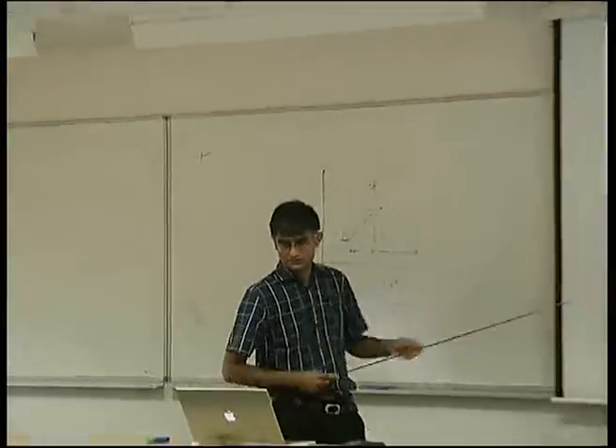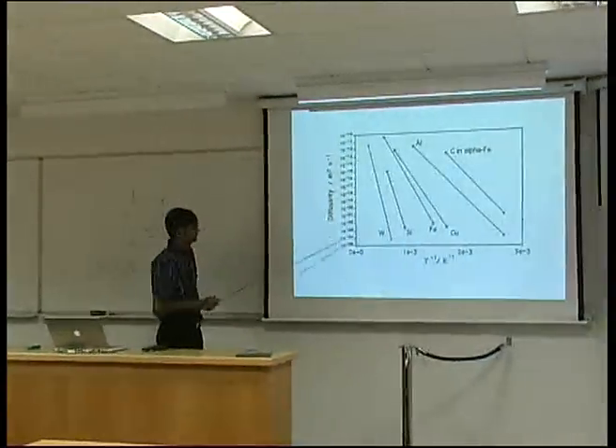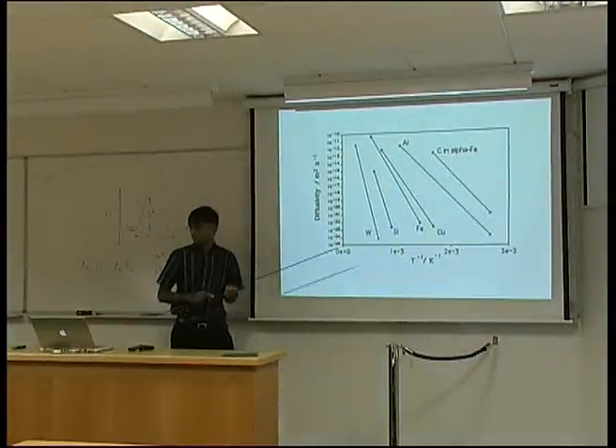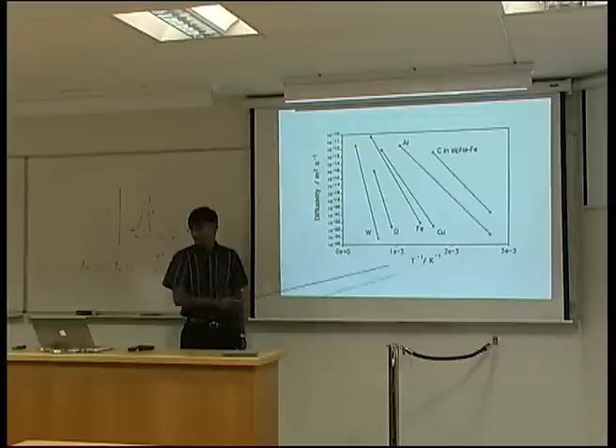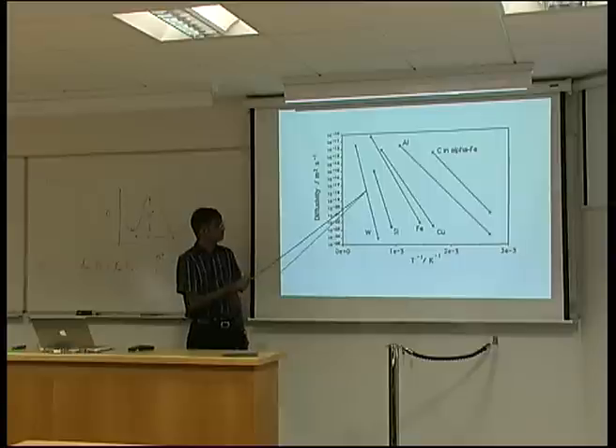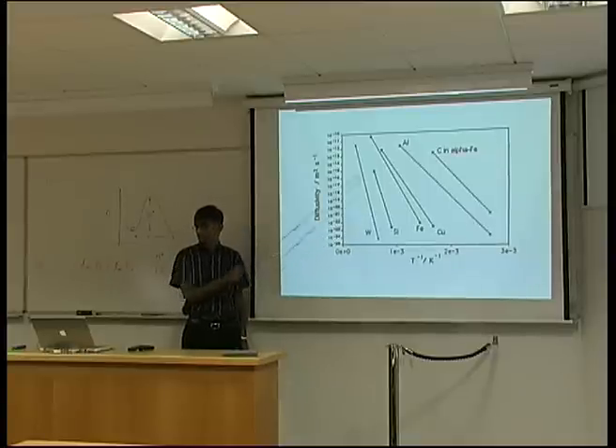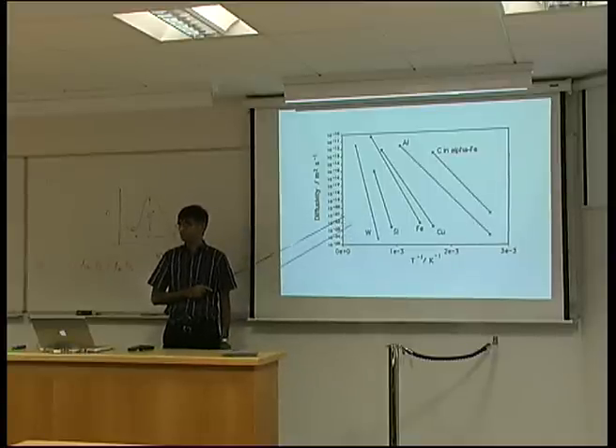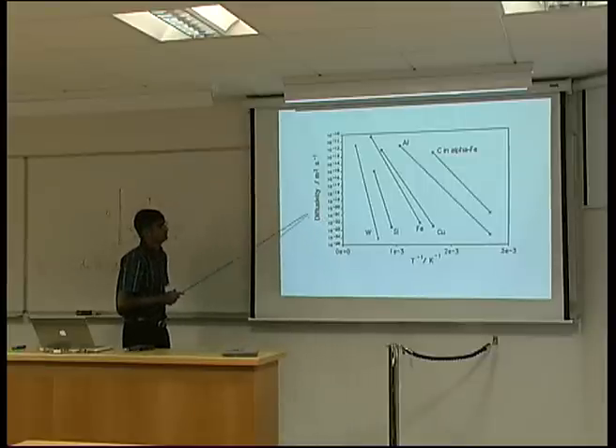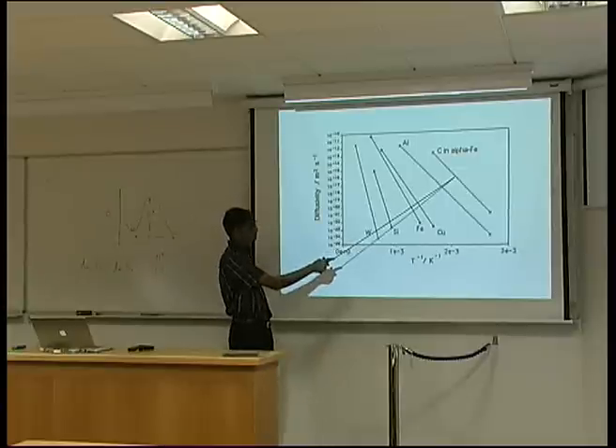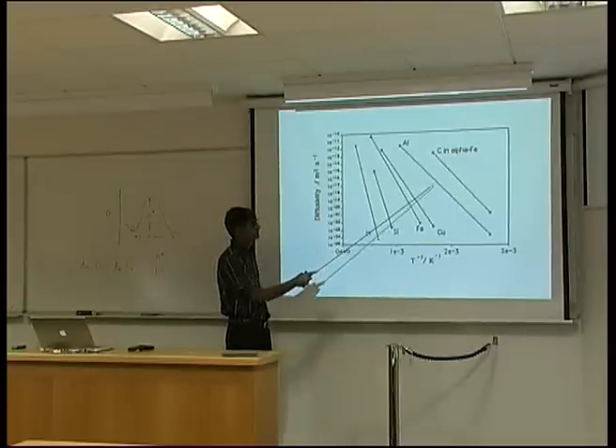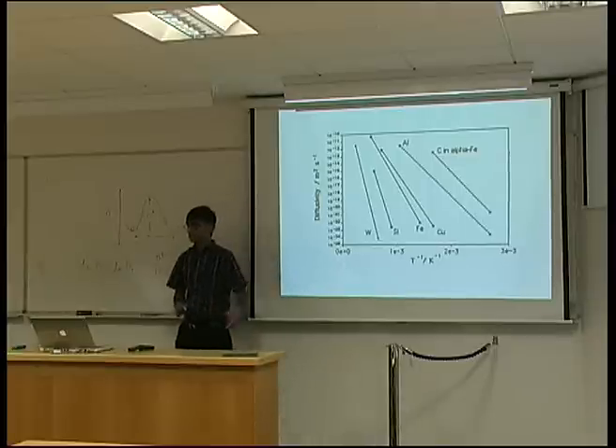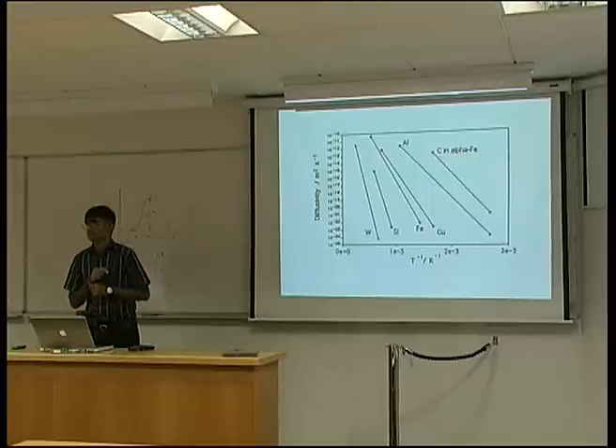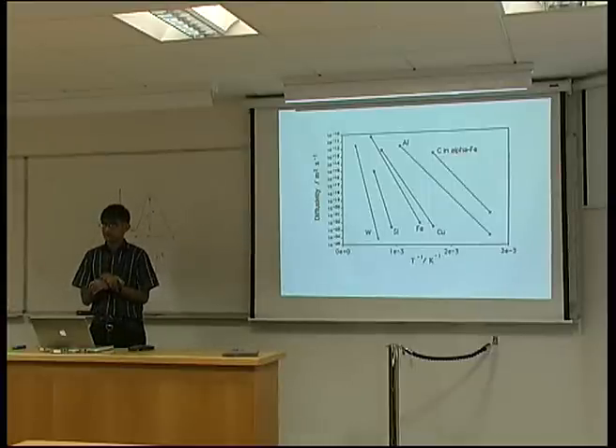So here are some typical graphs where we are plotting the logarithm of diffusion coefficient versus the reciprocal of temperature. And you can see that they are straight lines. I mean, this is just my drawing, that there are points at each end, because I didn't want to plot several points. Okay, that's laziness. But obviously you have to have more than 2 points to know that it's a straight line. Okay. What I'd like you to comment on is, why is the diffusion coefficient of carbon so much higher, many, many orders of magnitude higher, than, say, of copper in iron?